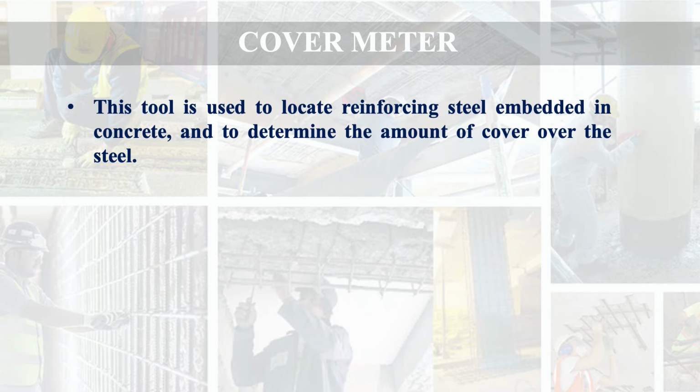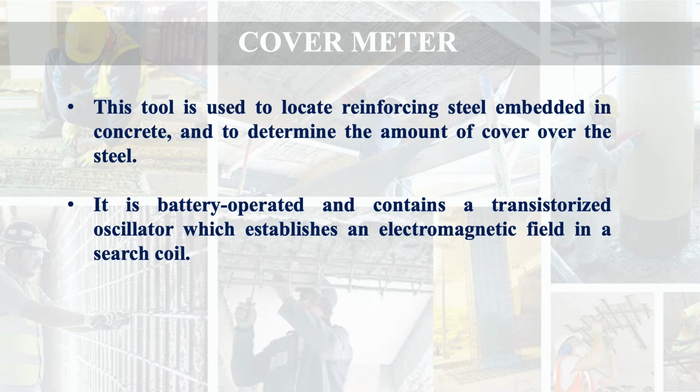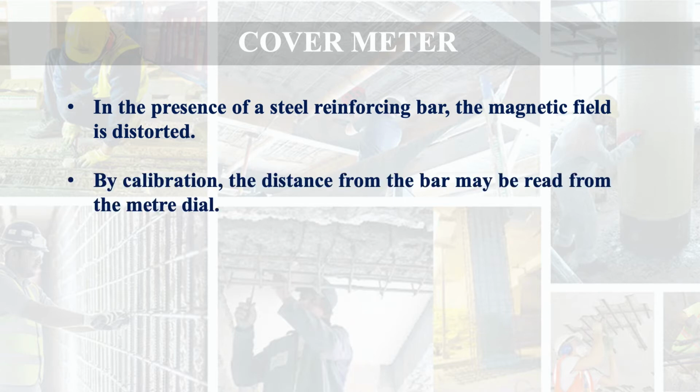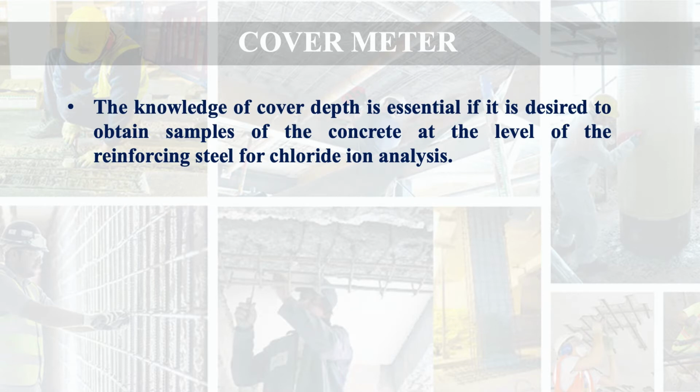steel. It is battery operated and contains a transistorized oscillator which establishes an electromagnetic field in a search coil. In the presence of a steel reinforcing bar, the magnetic field is distorted. By calibration, the distance from the bar may be read from the meter dial. The knowledge of cover depth is essential if it is desired to obtain samples of concrete at the level of reinforcing steel for chloride ion analysis.